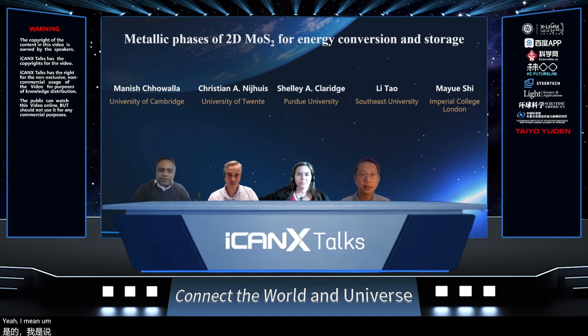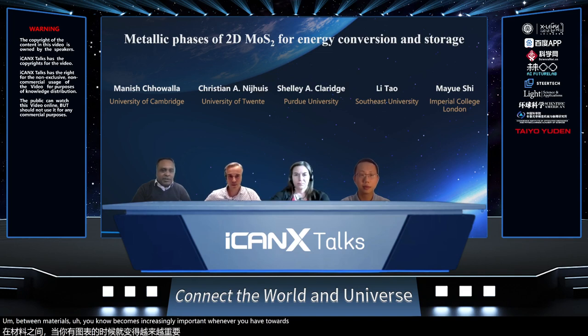Yeah, interfaces and contacts between materials become crucially important whenever you have charge transfer, right? And in the case of the battery, these electrodes are placed on copper or aluminum, and the interface and the contact between those have to be very good. There is some engineering to be done, but there's very little flexibility in moving away from these materials because they are quite cheap and well established within the battery field.